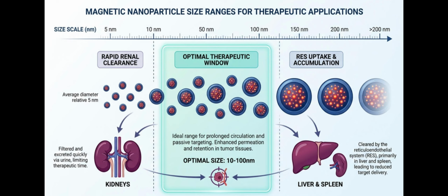In ferromagnetic and ferrimagnetic particles, the main mechanism is called hysteresis loss. As the magnetic fields alternate, the magnetic domains inside each particle continually reorient, creating a hysteresis loop in the magnetization curve. The area of this loop represents the amount of energy converted into heat per cycle. In superparamagnetic nanoparticles, which are smaller and contain only a single magnetic domain, heating is mainly produced through Néel and Brownian relaxation. In Néel relaxation, the magnetic moment flips direction inside the particle in response to the external field. In Brownian relaxation, the entire particle physically rotates within the surrounding fluid, producing frictional heat.